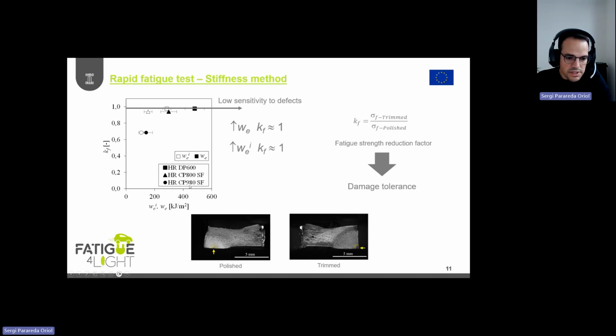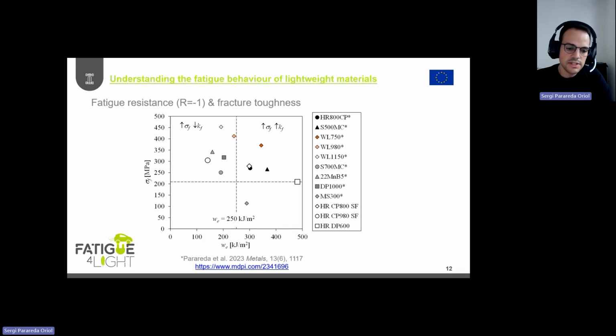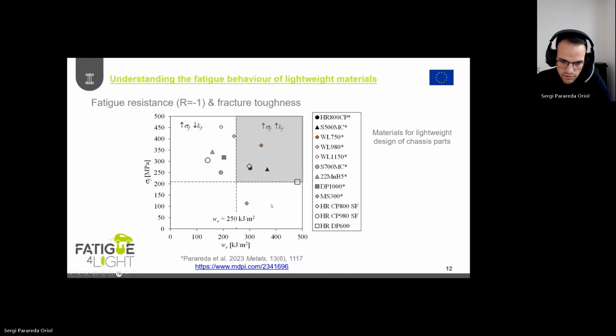And for instance, for this CP grade, this might be related to the fracture toughness of the material, since fracture toughness is related to damage tolerance. So here, as mentioned, this is the tool that I mentioned. Here we can plot the fatigue resistance for the polished conditions obtained by the stiffness method. We can easily obtain this data in 2 or 3 hours, and then we can also plot it against the fracture toughness. Fracture toughness can also be obtained in a short time, and by plotting all of this data, we have a chart to select the best materials for a lightweight design of chassis components.